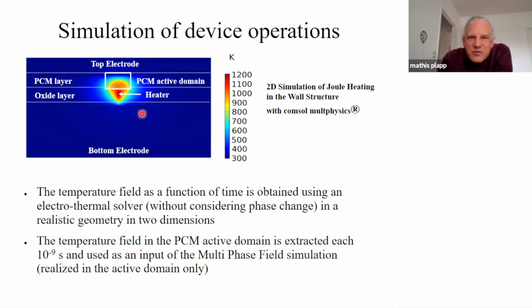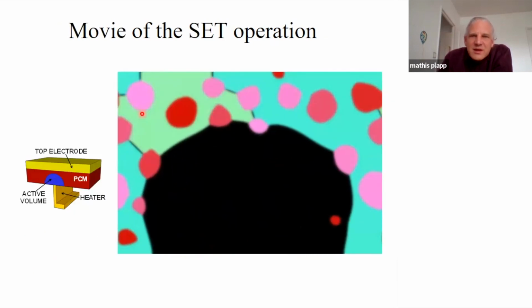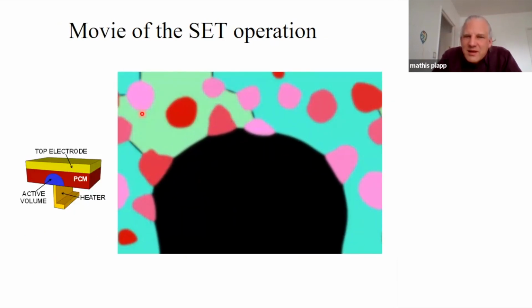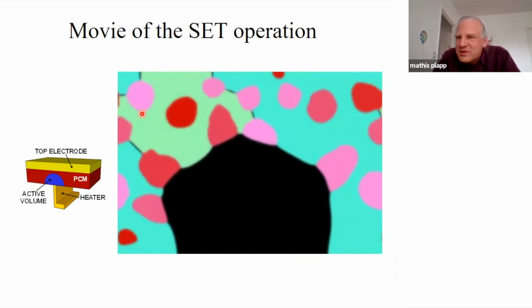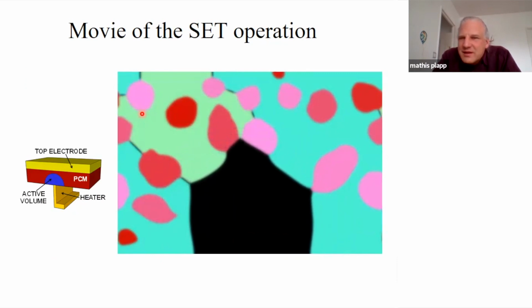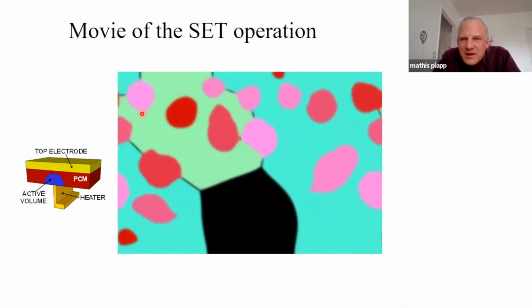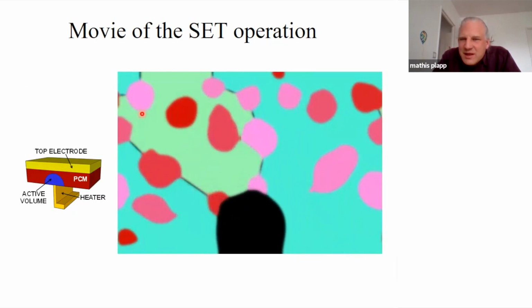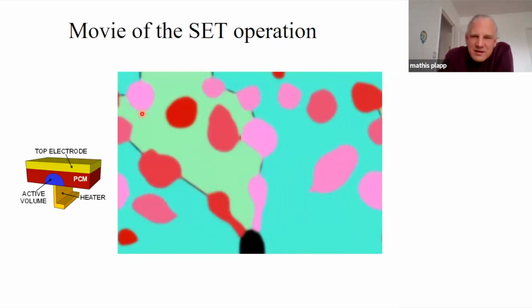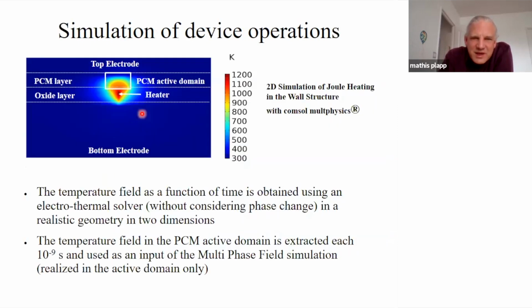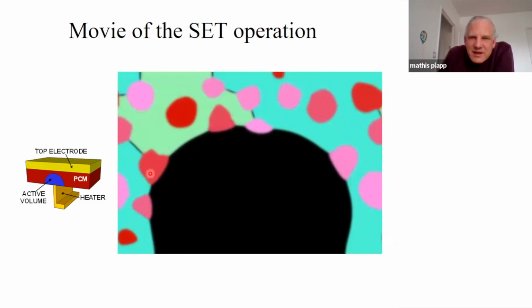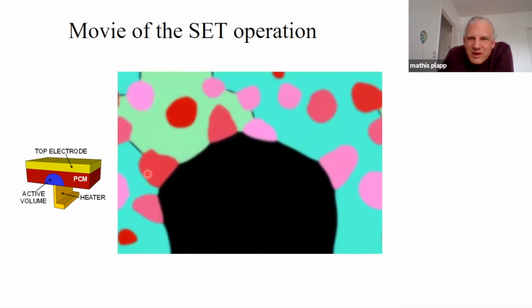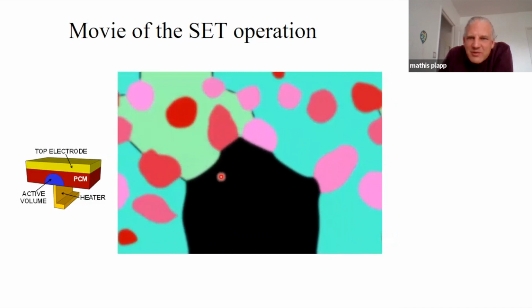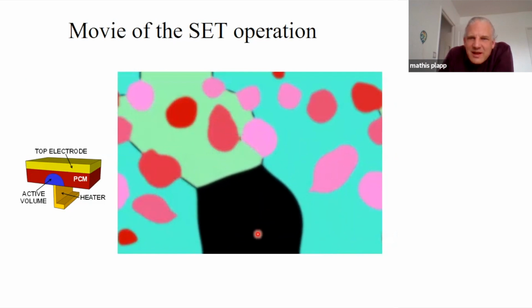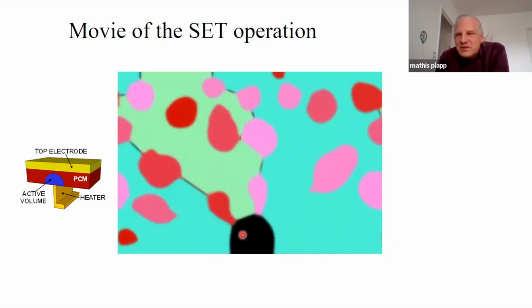And so for this one, I have a movie that will play there now. Okay, so the black is the amorphous phase, and when the system heats up, there is a melt pool that forms in the material. We take as an initial state the annealed film that we have produced in the previous simulation, and now the temperature goes down again, and you see that the system crystallizes, and at the end, the amorphous phase has disappeared. I'll play it once more. Because you can see that here the germanium grains grow first quite a bit, then they are all engulfed. So there is a portion of the sample where there's only GST phase. And then at the very end, the germanium phase appears anew in these trijunction points. This is something that we do not yet fully understand, but.